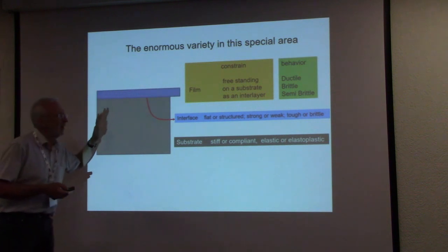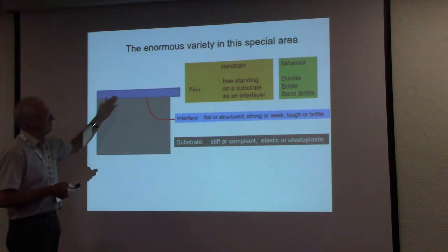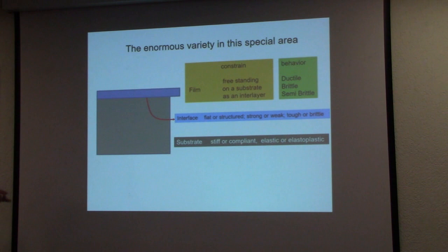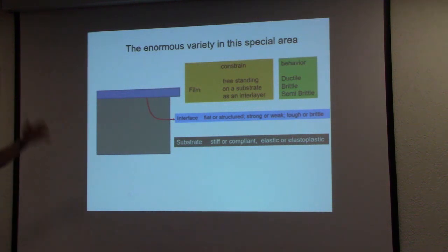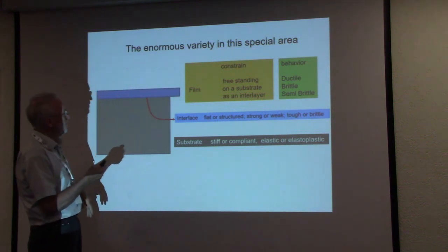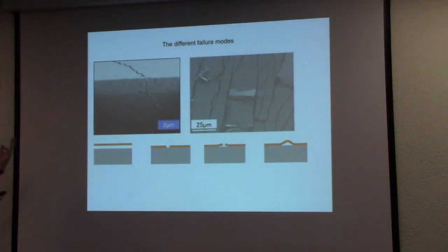The films, if they are metals or ceramics, then the ceramics have a fracture strain of few per mil, or if you have metal, then you have a strain of few per mil where plasticity starts. And this makes the consideration of these problems quite difficult, or there are so many different types of cracking phenomena that it would require a few days course.